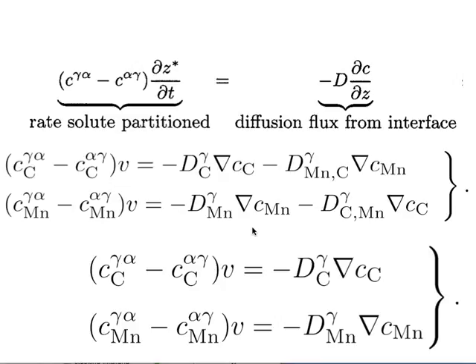So there's a problem. We've got to satisfy both of these equations simultaneously, but the diffusivity of carbon is huge compared with manganese, and the other terms in this equation, they are different, but they are certainly not different by 8 orders of magnitude. Okay? So if you can't satisfy this equation simultaneously, you can't maintain equilibrium at the interface. Okay? So we've got to find a way of doing that.